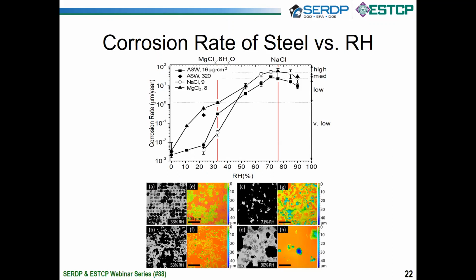All right, so let me just orient you to this first figure here. What you see is on the x-axis relative humidity and then corrosion rate. So these were samples that had a matrix of sodium chloride or other droplets put on them. And you can see the corrosion rate after 1 month of exposure. And on the right, you see what are considered the ISO levels of high, moderate, low, and very low corrosion rates that you see in the field.